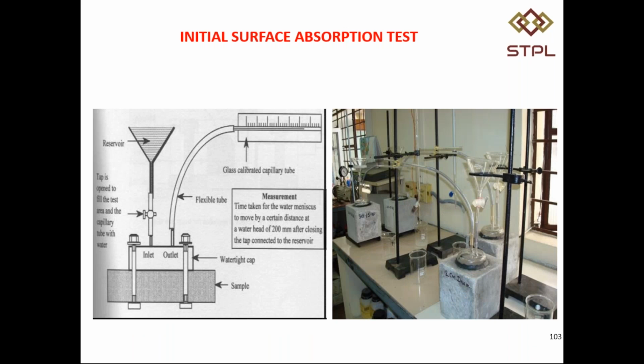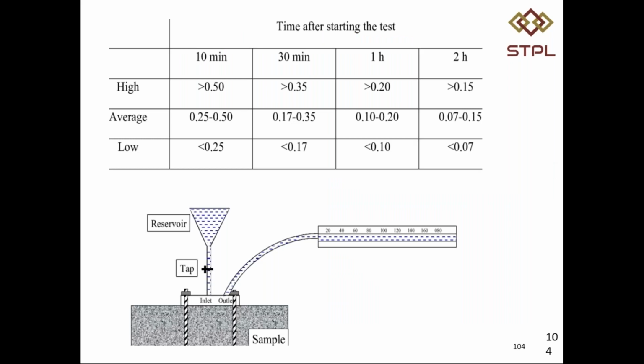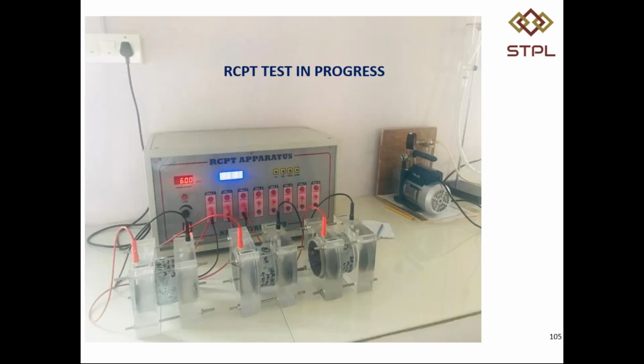Another useful test from the durability point of view is the initial surface absorption test, which gives the surface characteristics of concrete, whether the surface is dense enough, whether it is sound enough, which will not absorb much water. So it's a surface absorption value we find out after 10 minutes, 30 minutes, 1 hour, and 2 hours. And then the average and low values are specified here. So this is a very simple test to know the surface characteristics of concrete.